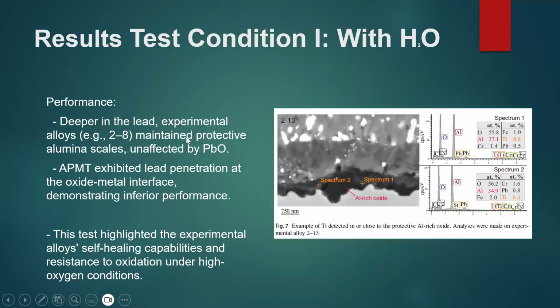For performance deeper in the lead, experimental alloy sample 2-8 maintained a protective alumina scale unaffected by PbO, while APMT exhibited lead penetration at the oxide-metal interface, demonstrating inferior performance. This study highlights that the experimental alloys have self-healing capabilities and resistance to oxidation under high-oxygen conditions.